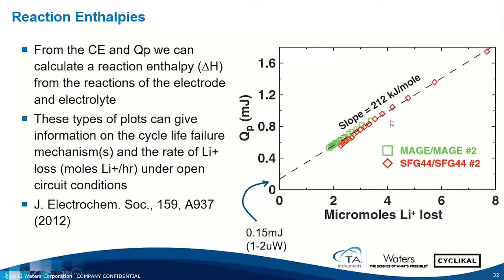And you can see I get a straight line. And the slope of that line is the composite reaction enthalpy. And as I said, it's a composite because we have more than one component in the electrolyte. And importantly, for both types of graphite, even though they have higher parasitics because of their surface area, the reaction enthalpy is calculated to be the same. And here is the reference behind that.